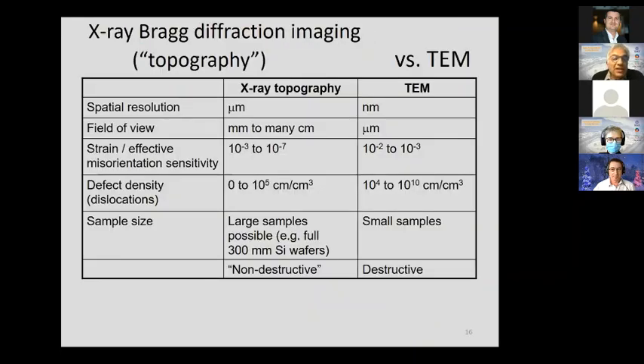Well, let's compare X-ray Bragg imaging with transmission electron microscopy. The spatial resolution is in the micrometer range, and of course in the nanometer range for transmission electron microscopy, you cannot compete, but the field of view is millimeters to many centimeters, and is only about 1 micron in transmission electron microscopy. And the angular sensitivity is a lot better for X-ray topography. You can see 10⁻³ to 10⁻⁷ radians when you are limited to 10⁻² to 10⁻³ in transmission electron microscopy. The defect density you can look at is up to 10⁵ dislocations per square centimeter, and that is 10⁴ to 10¹⁰ for transmission electron microscopy.